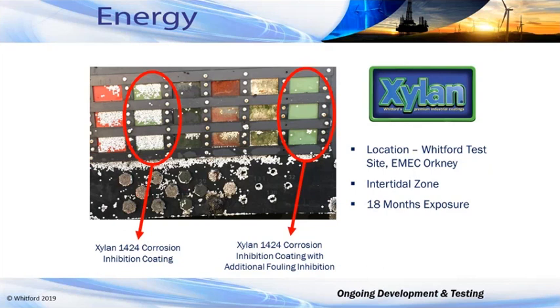And circled on the left-hand side, you can see one of our more common coatings, Xylan 1424, which is simply a corrosion inhibitor. There is no fouling inhibition properties within that particular coating formulation. Exactly the same coating we've taken and added some fouling inhibition properties into it using various chemistries and ingredients.